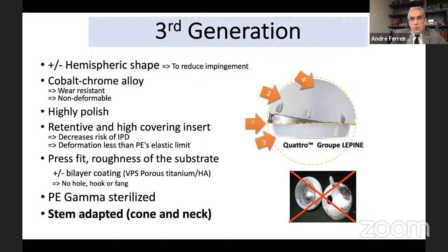Now we try to have a very hemispheric shape to avoid important contact impingement between the neck and the shell, with a cobalt alloy to avoid any deformation of the shell into the bone, to avoid blocking the insert, with a retentive rim covering the insert in polyethylene to decrease the risk of intra-prosthetic dislocation, and with a press fit and with a roughness of the substrate with or without hydroxyapatite or VPS porous titanium. Polyethylene is gamma sterilized, we will see that, and with a very adapted stem, of course, about cone and neck.